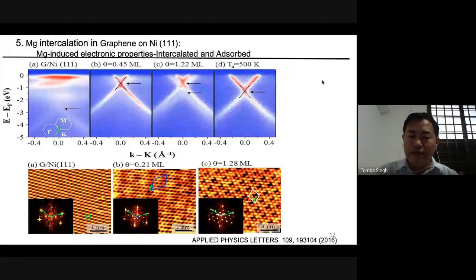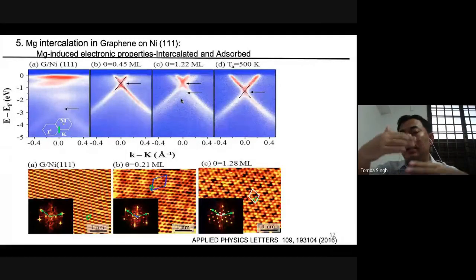The different bands we observe are given here. These bands are taken at the K point, where we can see the Dirac cone. This is the pristine one, so no proper Dirac cone. But at low coverage, the Dirac cone appeared. As we increase the coverage, we observe two Dirac cones. Where is this arising from? This is coming from the interaction with the adsorbate, and the other one is the graphene interlayer. So from this interaction, we got two Dirac cones here.